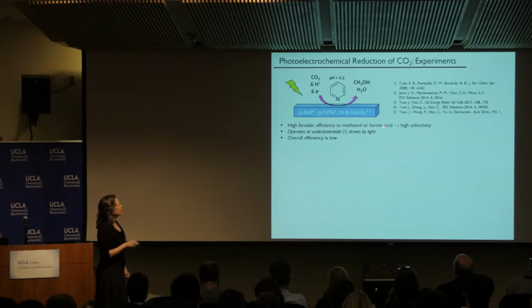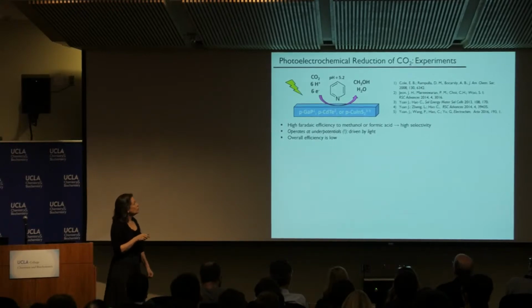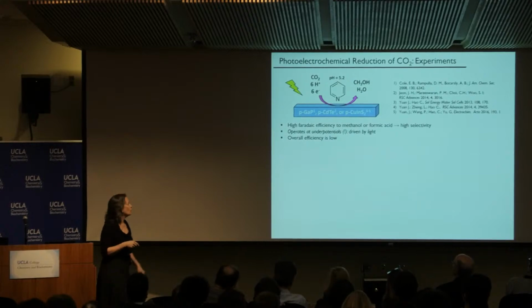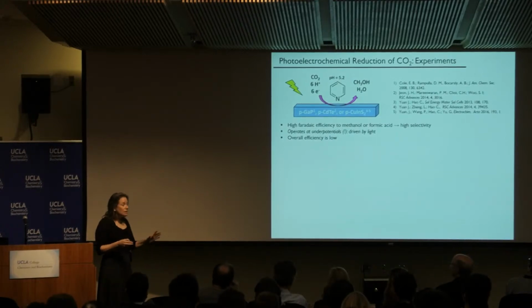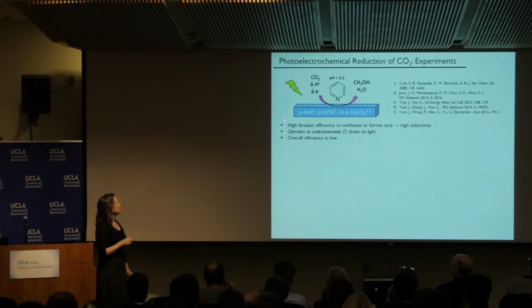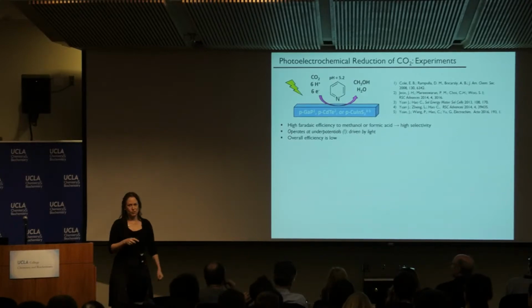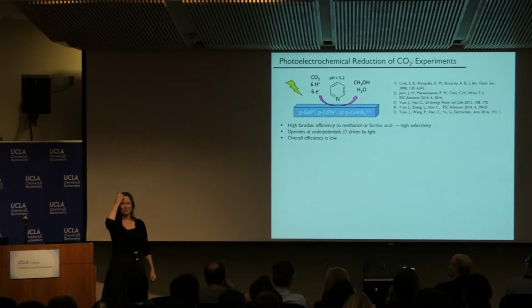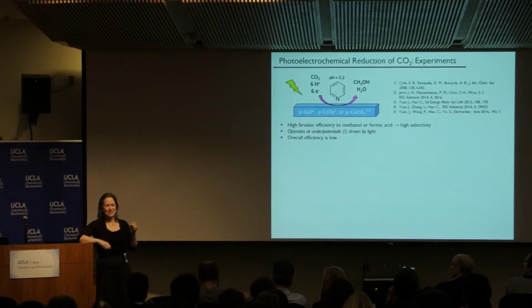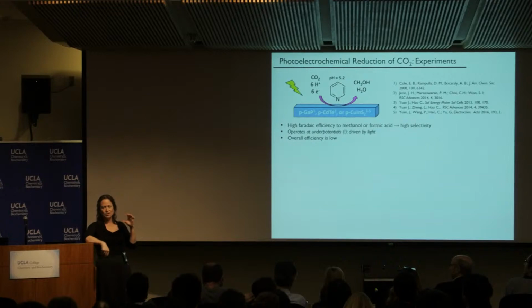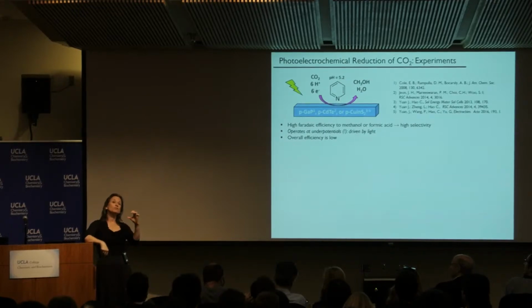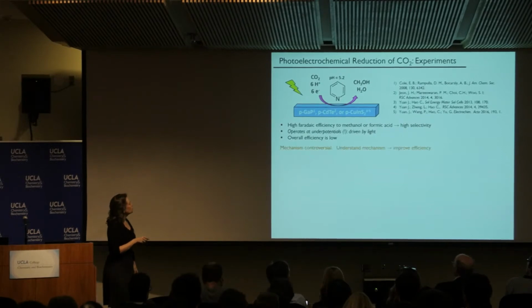So very selective. That's extremely unusual. If you don't have the pyridine, you don't get the selectivity. So pyridine is clearly playing an important role. You don't get the same products. And the other thing that's amazing is it operates at underpotentials, which when I first heard that, I thought, what on earth does that mean? Well, what it means is that you don't have to apply the full thermodynamic voltage associated with the reaction, because the rest of the energy is coming from the light, from the excited electrons. So that tells you it's being driven by light.